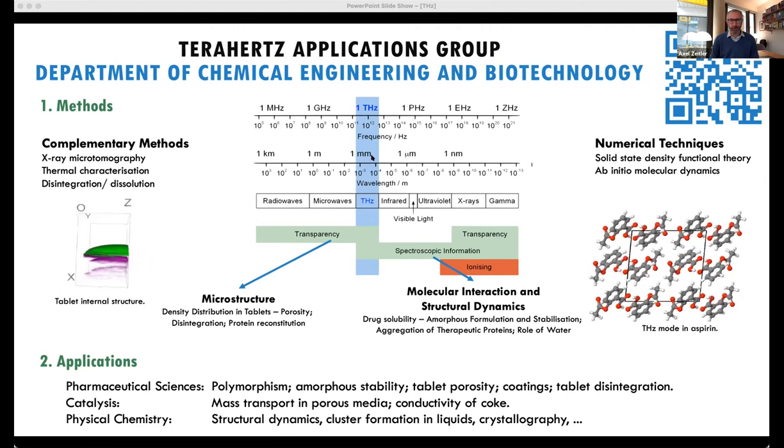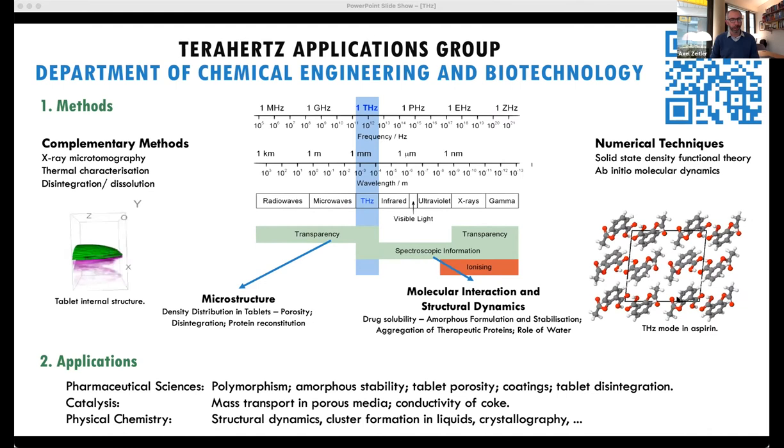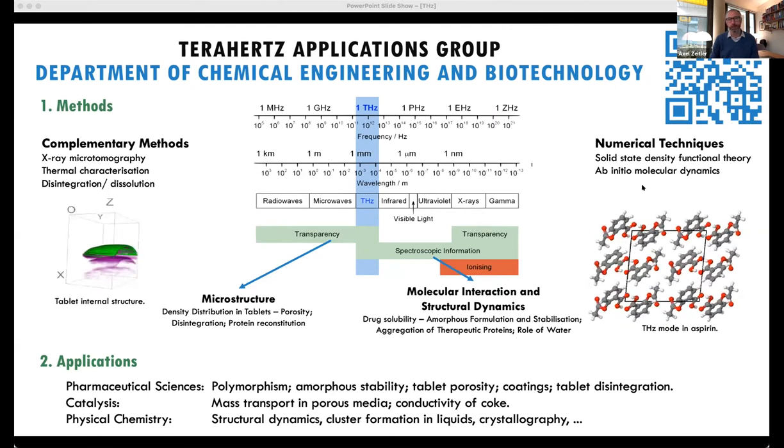And so when we started out, we looked a lot into crystals, and here you can see the motions that you would observe at terahertz frequencies are essentially the entire molecule moving, translating, for instance, here the phonon vibrations, but they're often coupled in rotations and translations, twisting motions in the organic molecules because they're quite flexible. And so we can find out a lot about the crystal structures and the dynamics of the crystals and how the structure interacts with the dynamics. And to do that, we use ab initio molecular dynamics simulations, but also solid state DFT calculations.